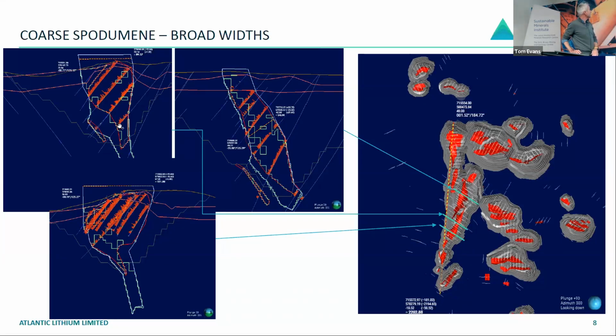Now, this is an area, obviously, that we're trying to do more studies on and try to build a system where you can actually map P1 versus P2 from multi-element geochemistry or something else, because most of this drilling is RC, and that's texture destructive. So it's hard to log grain size in your RC drill chips. And so we use diamond core, and now the guys have got their eyes in, they're getting better to pick up that coarse grain versus fine grain, but it's still not quantitative, it's qualitative. So that's something that we're trying to do some studies on, looking at multi-element geochem to see how we can really bed down that P2 mineralization.